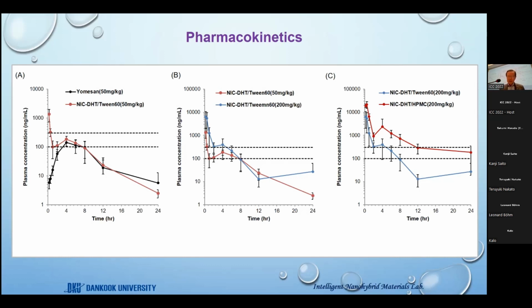In the middle, the PK profile was subsequently optimized by changing the dose and the non-ionic polymer coating. The highest NIC concentration in plasma observed at 15 minutes was significantly enhanced when the dose was increased from 50 to 200 milligram per kilogram. We found that about a 5-fold increase of the highest niclosamide plasma concentration could be observed by dose increase. However, the time required to sustain the plasma concentration of NIC above IC50 remained at only 8 hours.